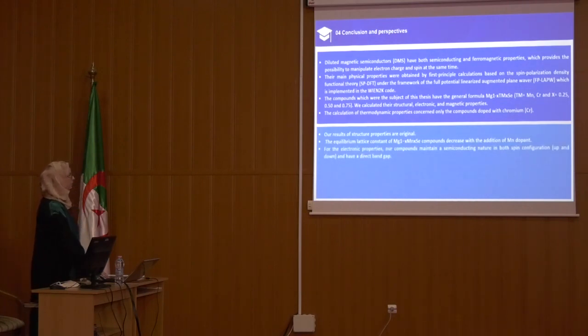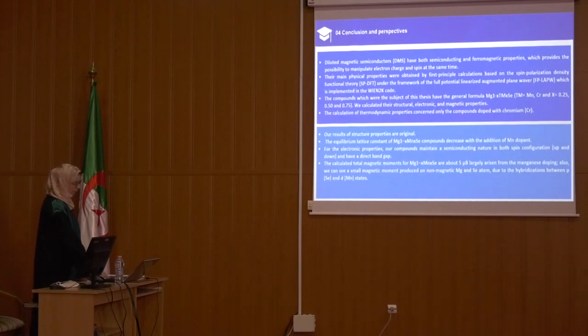For the electronic properties, our compounds maintain a semiconductor nature in both spin configurations and have a direct band gap. The calculated total magnetic moment for MgSe doped with manganese is about 5, largely arising from the manganese doping. Also, we can see a small magnetic moment produced on the non-magnetic Mg and Se atoms due to the hybridization between p-Se and d-Mn states.